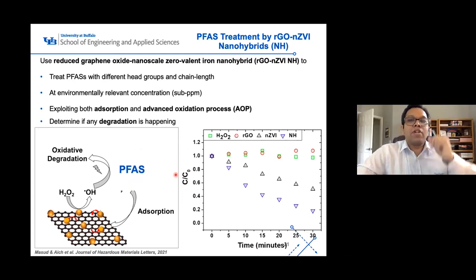So we are trying to solve this problem by using reduced graphene oxide nanoscale zero valent iron nanohybrid, rGO-nZVI. One process is, can we adsorb these PFASs on the surface of these hybrids, or can we use the catalytic property of the iron to degrade these PFASs on the surface of the nanohybrid? So what we are trying to do is take several PFASs with different head groups and chain lengths at sub-ppm level concentration.